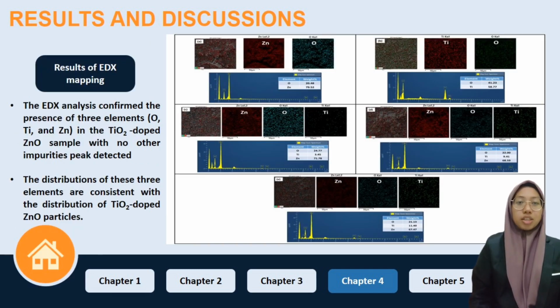Further characterization of the elemental composition of titanium dioxide doped zinc oxide was conducted using EDS chemical mapping analysis. The EDS analysis confirmed the presence of 3 elements, which are oxygen, titanium, and zinc, in the titanium dioxide doped zinc oxide sample. The distribution of these 3 elements is consistent with the distribution of the titanium dioxide doped zinc oxide particle. It shows the presence of these 3 elements with no other impurity peaks detected in the EDS spectra, confirming the purity of the sample.